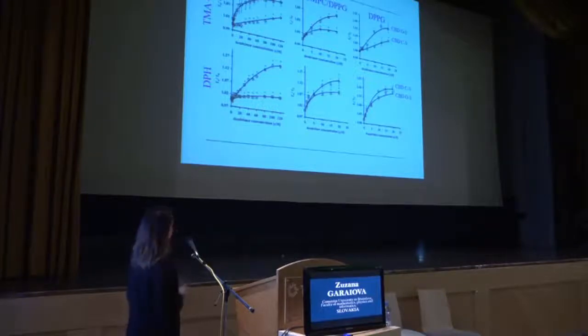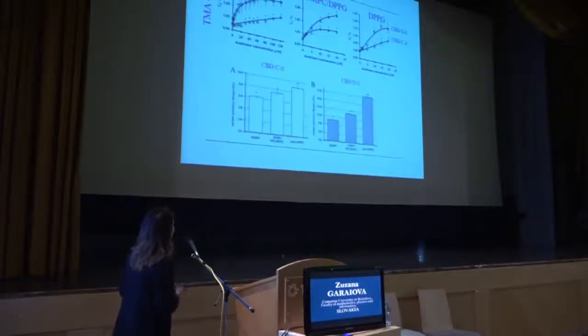And in the case of lipid vesicles, we were analyzing fluidity of this membrane by measuring fluorescence anisotropy, and we were monitoring the region of polar head groups as well as the hydrophobic core using 2 commonly used fluorescent probes, TMA-DPH, that is located in the hydrophilic region, and DPH that is located inside the hydrophobic core of the membrane. And this kind of model membrane, this liposome, we were also analyzing by means of size and zeta potential measurements.